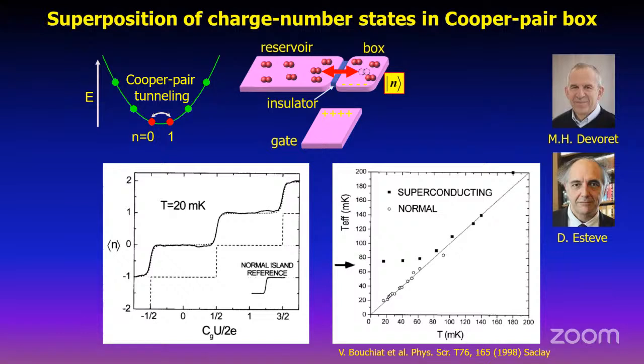At most one Cooper pair can tunnel in and out because of the large charging energy. Now you remember that in a large scale Josephson effect, all the charge number states are degenerate because we neglected the charging energy. Here, because of the charging effect, different charge number states have different energy due to the Coulomb energy, like a quadratic form. So if you choose the parameters correctly and then apply the gate voltage bias to adjust the origin of this parabola, we can create a situation where only two charge number states are nearly degenerate.